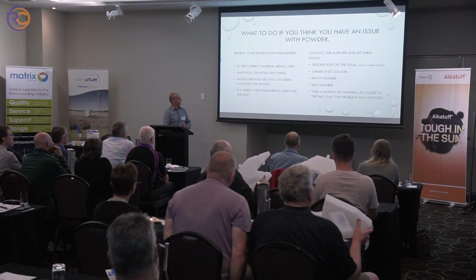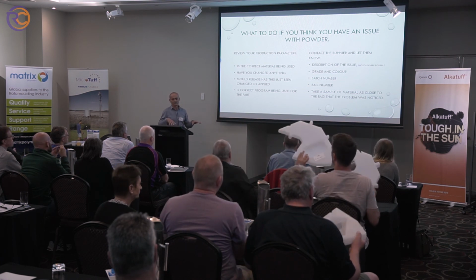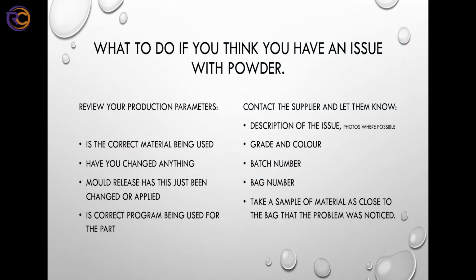One quite common one is blocked breather tubes. When you get blowholes in the parting lines, you can have issues, and it's not a powder-related problem. Mould release, David's talked about, over-application of mould release can affect the surface finish. And also, we've seen cases where, for instance, making kayaks, the moulder has preheated a certain area to get more material into that area, but he's put too much heat in, and so the powder hits it and melts straight away, but doesn't have enough time to actually fuse out and melt out, and it creates voids in that area. And obviously, if the correct program's been used, if the mould's been put onto another machine or placed on the machine differently, it will all affect the way the material is going to flow in the mould.